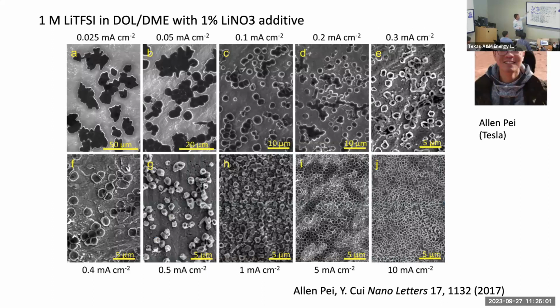And we find that with smaller driving force, you see these big nuclei, 50 micron scale bar, but once you go to 10 milliamp per centimeter squared, you see the nuclei size becomes so much smaller. And then you can count it, you can measure. It fits classical nucleation theory so nicely, the scaling law. And why is this important? Because this determines the size of lithium metal that will affect the battery performance later.